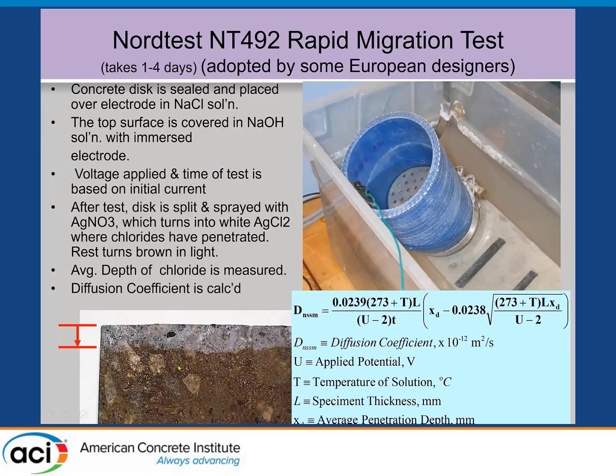And where the silver nitrate persists, where there are no chlorides, under light after a few minutes, it turns dark brown. So you can visually see the chloride penetration. You can measure every centimeter or half inch across and get the average penetration. And you can actually plug that depth into this equation, which looks complicated, but it's only temperature and length and voltage and time. And there's the penetration depth, and you can calculate a non-steady state diffusion coefficient, which some people use in diffusion service life models. So people have jumped on this in Europe because you get a diffusion value. I'm not convinced that diffusion value is the right one to use, but anyway, that's fine.